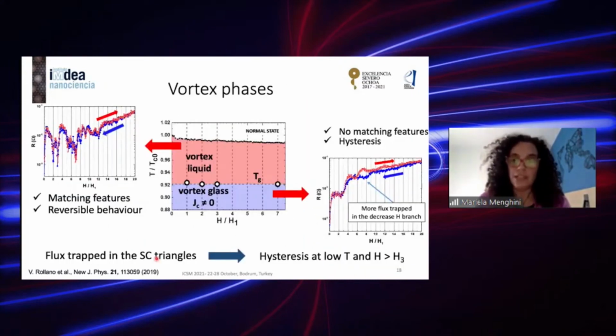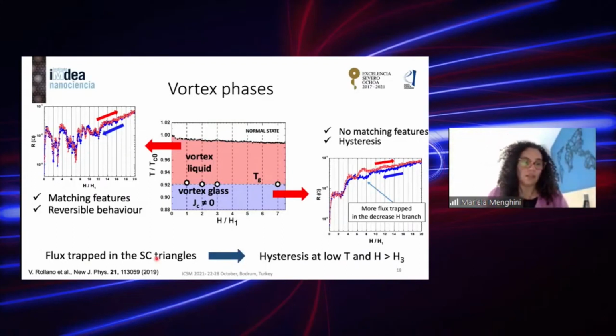So to finalize, the other thing that we looked into is the magnetotransport in this high temperature region, more like the vortex liquid phase, compared to the low temperature case. And what we see is that at high temperatures, the matching features in the magnetoresistance are very clear, and actually there is also reversible behavior when we sweep the magnetic field up or down.